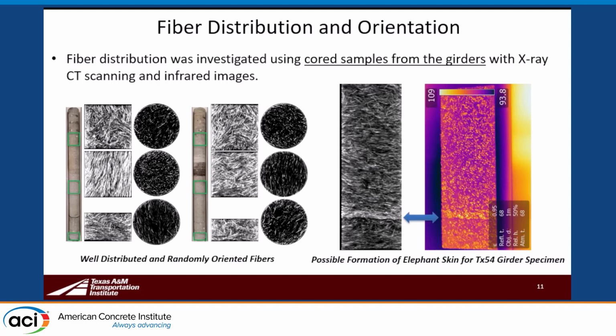We also looked at fiber distribution and wanted to see how well the fibers were distributed in our girder specimens. So after we tested the girders, we took some cores through the section of the web, and these green rectangles just show where these various X-ray CT images are being taken. We do see some different alignments of the fibers in different locations, but overall we're seeing good distribution of the fibers, and then perhaps depending on how the pour was done, in the direction of the pour, we may have a little bit of alignment in some of these cores.